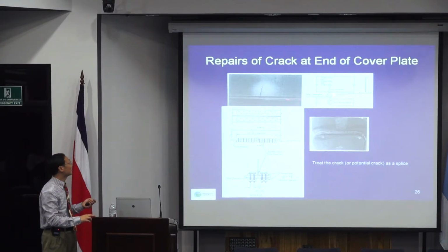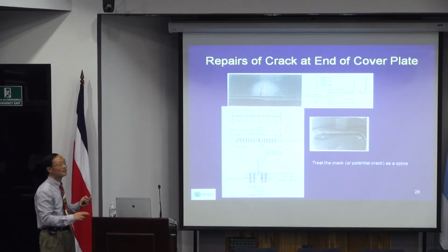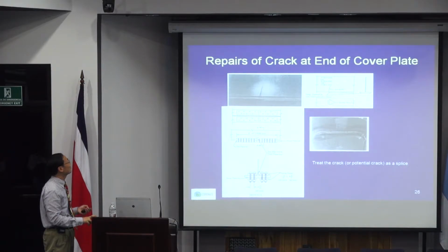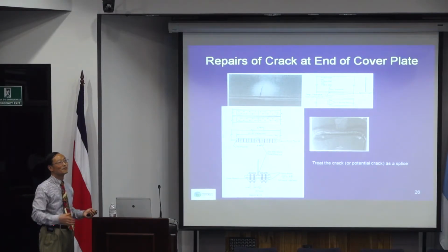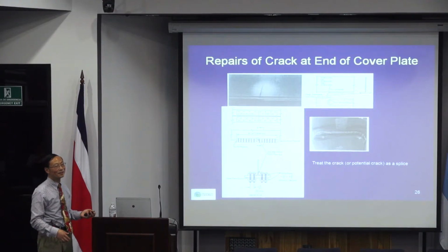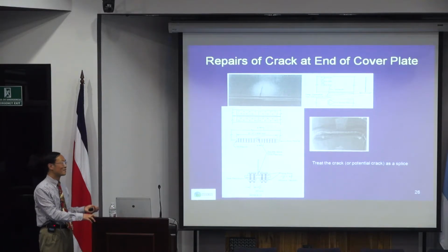But that's okay. But these cause stress concentration, as I said. Once the stress concentration is very large, that causes a fatigue crack. So that's why this kind of cover plate is not allowed in most jurisdictions. If you already have the crack problem, that bridge has already collapsed, so you don't have that scenario. But you may have the concern of what happens if it develops into a crack. So what you can do is assume it's already cracked, although it's not cracked. You can put a splice plate, bolted, so we assume. Once you've done that, you effectively reduce the stress so much that it will not be able to develop a crack. Or even if a crack develops, you're not concerned because you assume it's cracked already. You treat that as a splice.